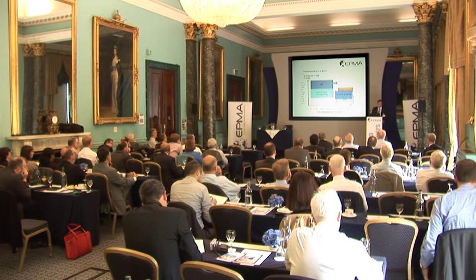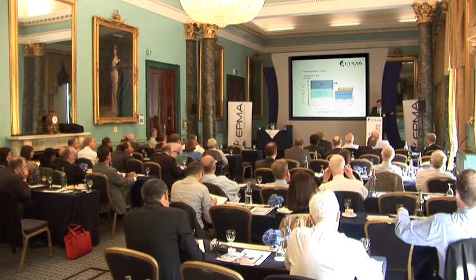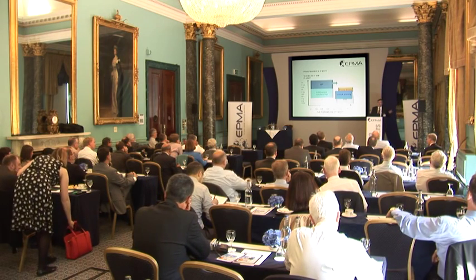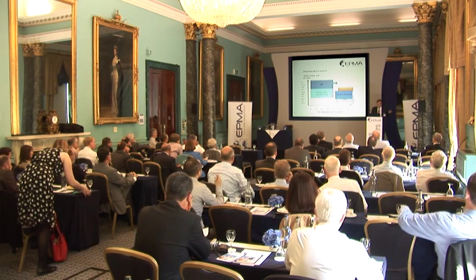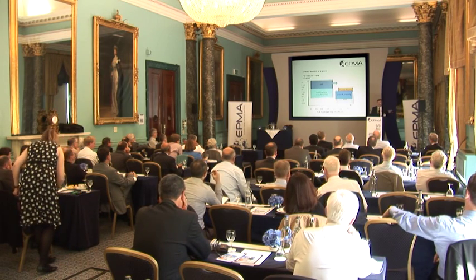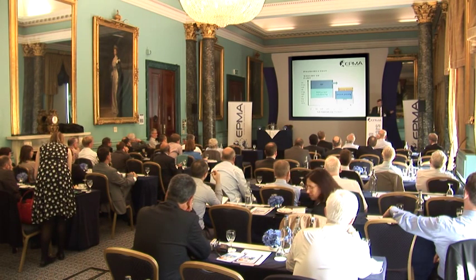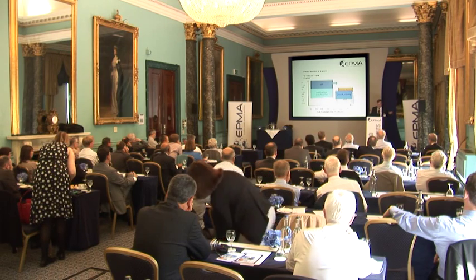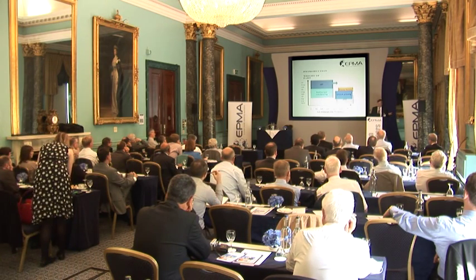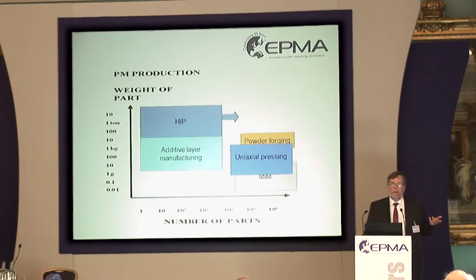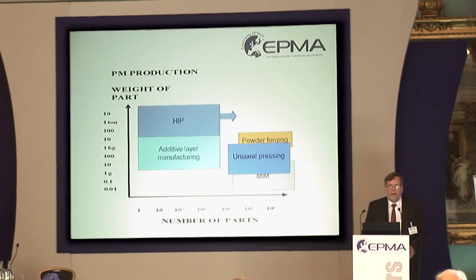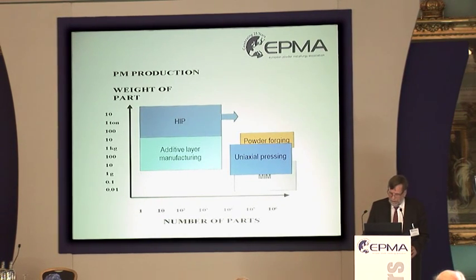And also, this shows what I say is the economical feasibility area for different forming processes. The number of parts is, let's say, in order of components. And on the other scale, you have the weight of the part. And for HIP, you have right now something from 20 kilos up to 30 tons. Minimum amount is 1. You can't go less. And then you have, let's say, 10,000 parts. And that is expanding. And also you can see the area for additive layer manufacturing fits in perfectly well in a field where powder metallurgy was not competitive earlier.